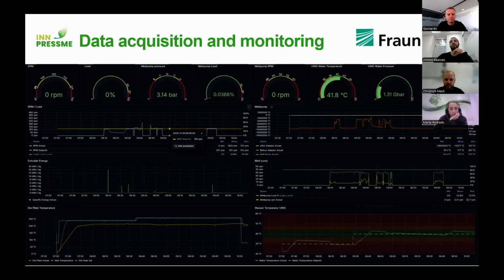And just to show you quickly one page of our system. This is the control system, which can be remotely accessed. So we see all values. This is an archive value, so not live in this case. From a few days ago, we see all kinds of sensor values that have been measured of the melt pump, the underwater pelletizer, the die plate, and we can see if there have been any anomalies. We can see if the values are in the desired range, and set points versus the values which actually exist. This helps a lot in checking for process control and also in the later analysis of the samples.